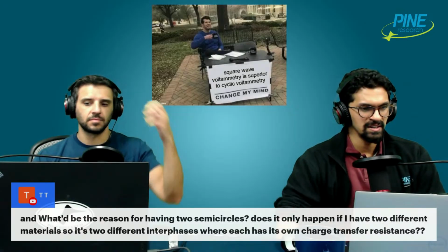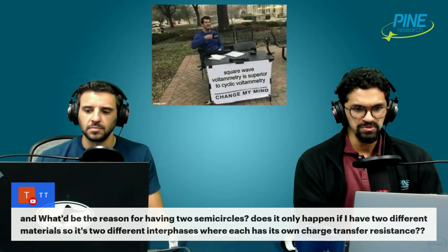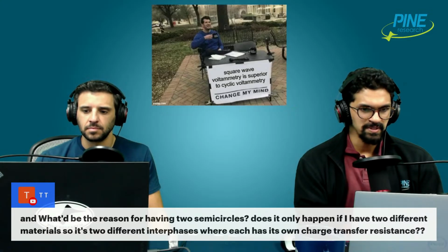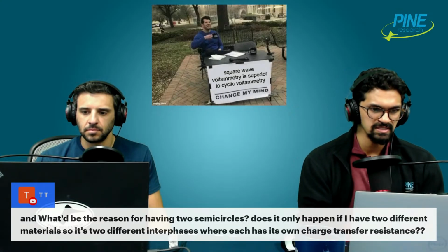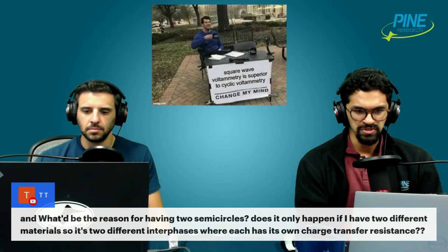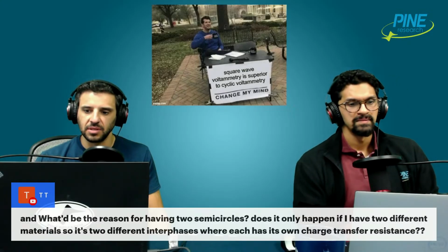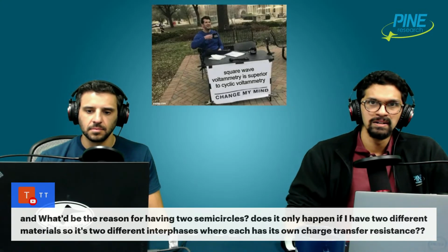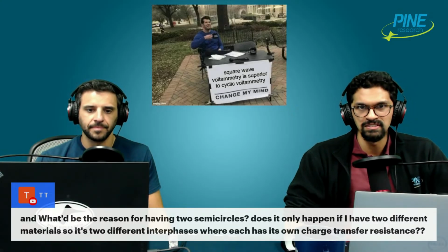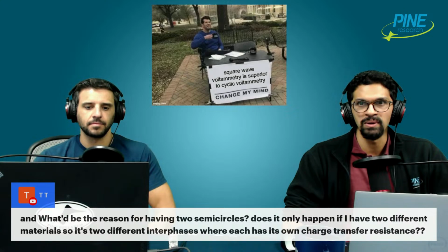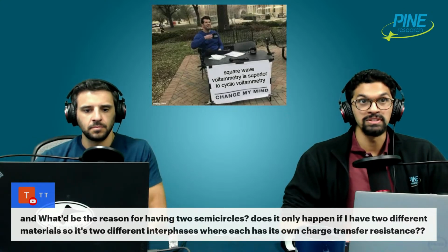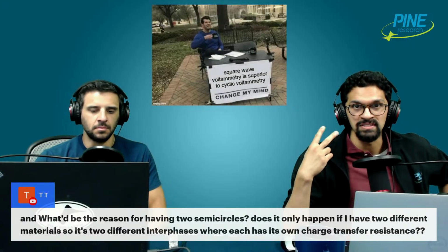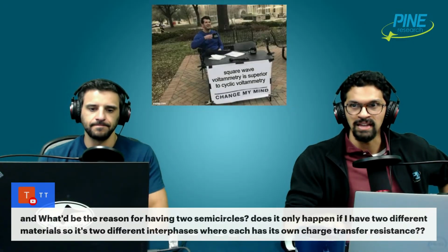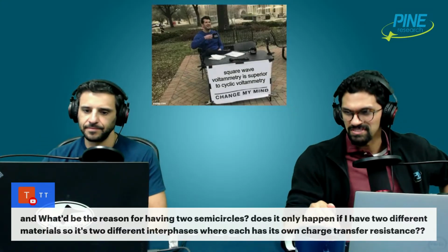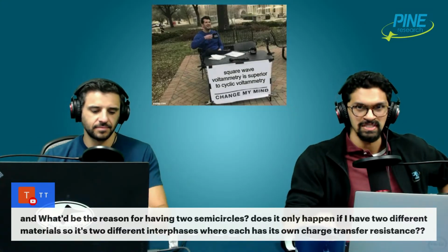TT asks, what would be the reason for having 2 semicircles? Does it only happen if I have 2 different materials? So it's 2 different interfaces where each has its own charge transfer resistance? That is a possibility. I think in general, just from a fundamental impedance standpoint, you can clearly identify 2 different processes that have 2 different time constants. You can say that with a large degree of certainty. They have 2 different time constants.